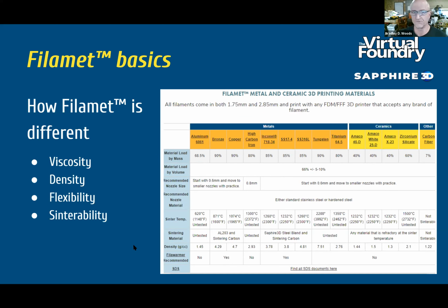So the key difference is that in the end, you can wind up with a pure metal part. The PLA gets removed during the debinding process, and it becomes a rigid object. The particles weld together during the sintering process. So, those are the key differences.